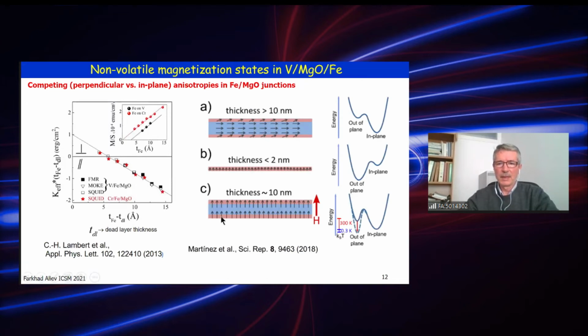Perpendicular magnetic anisotropy is present in very thin iron layers at room temperature, but in our structures we tuned thickness to about 10 nanometers, where, depending on the field history, we can create either in-plane or out-of-plane magnetization. This is a sketch shown here, and this paper explains how to create different non-volatile magnetic states in the system, or in a ferromagnet in contact with a superconductor, through the spin-orbit coupling.